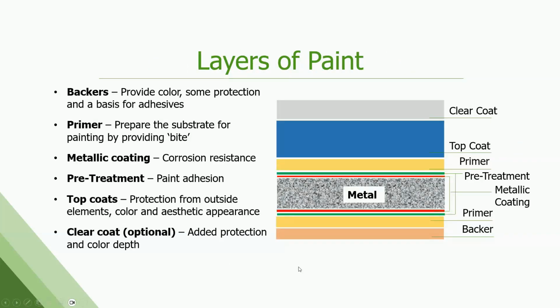The layers of paint, we talked a little bit about this. It's not just a single layer of paint. There's quite a bit going on here. So in your core, you have your steel or your aluminum substrate with your metallic coating. You then have a layer of pretreatment. This preps the surface to take paint, provides a bite, a point of adhesion for the primer that goes on. Put the primer on. The primers we're using all have corrosion inhibiting pigmentation in them because you're going to have cut edges and might have some exposure, so you want that protection there. We'll talk about severe environments later, but you can play with that primer to get a good product that's suitable for extreme conditions as well. Then you put your top coat on. If you need a clear coat, you would then put a clear coat on as well.